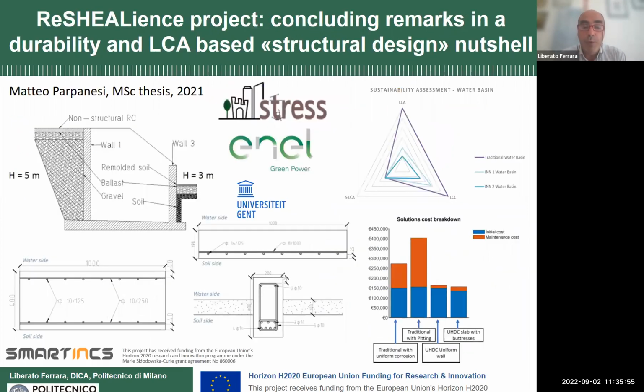And we ended up with redesigning our structure, and you can see these are some results of collaboration, which also continued with the Marie Curie International Training Network. We went progressively reducing the structure size using our ultra-high performance materials. And you can see here the life cycle analysis ended up with significant improvements, because we go from the purple peak to the blue ones that are for our different solution, and also the life cycle cost.